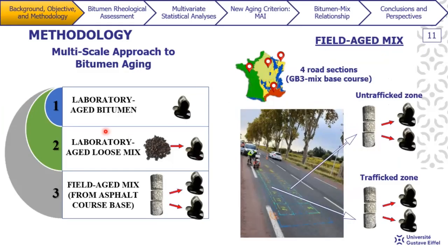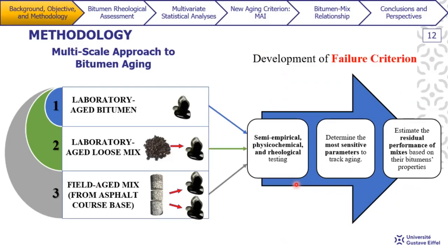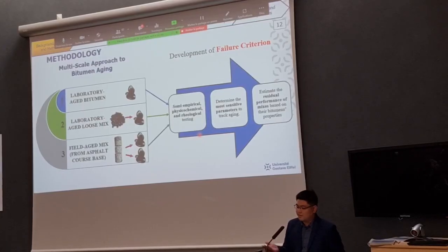And the last scale of our approach was the field aged bitumen, where bitumen was recovered from the asphalt course base. So here is just a map to present the location of each of these carefully selected roads. And all these roads, what they have in common, they have their asphalt base course formed by GB3 mix. And here this photo is just to illustrate what was done in each of these sections. So in each of these sections, asphalt mix was taken from the traffic zone, in this case in the right wheel path, and from the untrafficked zone, which was between these wheel paths. So this is the global overview of the methodology that I adopted to address the objective of my PhD work.